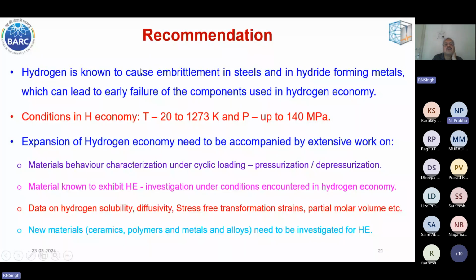My recommendation for future research is this: hydrogen is known to cause embrittlement in steels and hydride forming metals, which can lead to early failure of components used in the hydrogen economy. The conditions that will prevail in the hydrogen economy will span from 20 K to 1273 K, and pressure could be as high as 140 MPa. Expansion of the hydrogen economy needs to be accompanied by extensive work on materials behavior under cyclic loading, because even without hydrogen, pressure cycling and pressure release will cause fatigue loading because of pressurization and depressurization.